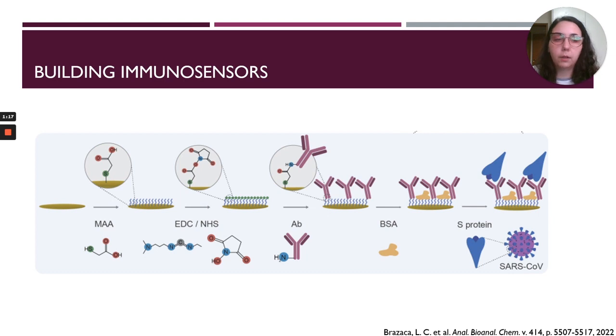Okay, so after characterizing the electrodes containing the electrodeposited particles, we have attached the specific antibodies to S protein so that we would build our immunosensors. So what we did for that was we first added mercaptoacetic acid so that the thiol group would bind to the gold, leaving carboxylic acid groups available for interaction. We then followed with EDC and NHS and made the covalent binding of the antibodies with their amino groups. As previously, we did the blocking with BSA, and then the sensor was responsive to the desired S protein.